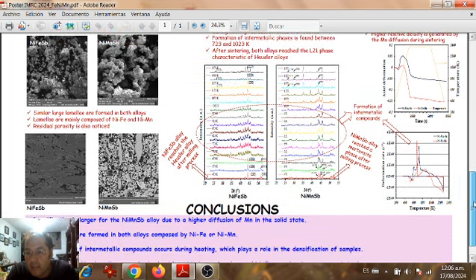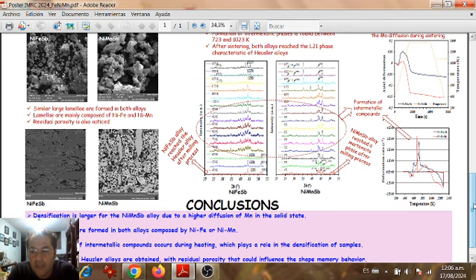So we notice that this process is to order the final phase recorded, that is the Heusler alloy, and we notice also that this has an effect on the densification of the sample. So for the nickel iron antimonium, we obtain a lower axial deformation, which is accompanied by a lower densification. The microstructure after sintering shows larger lamellae that are composed mainly of nickel iron and nickel manganese phases. These also show a residual porosity that is normally found between the particles.